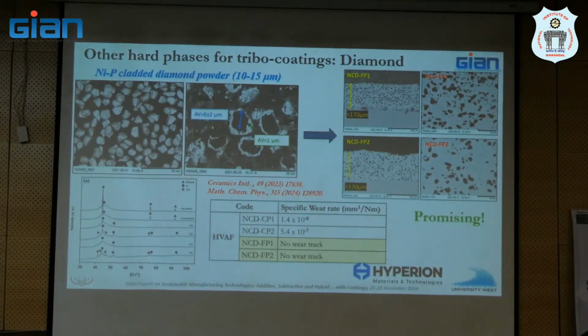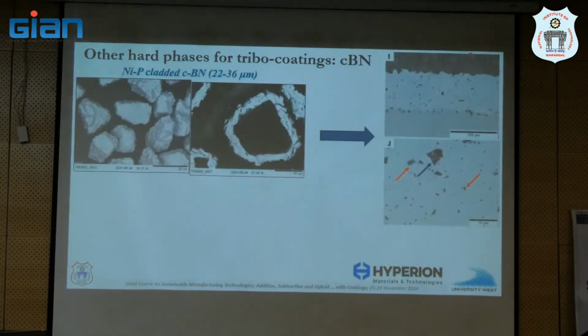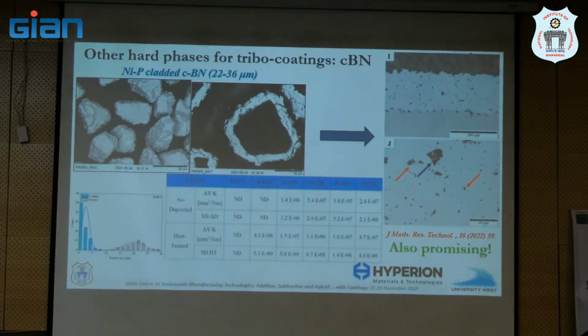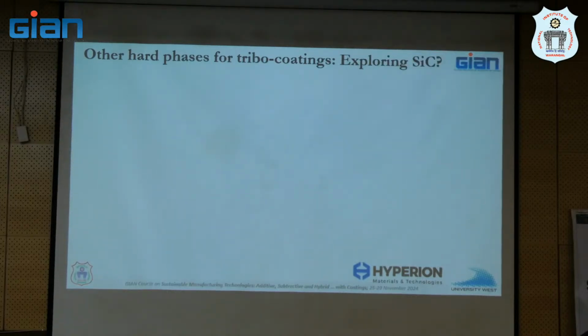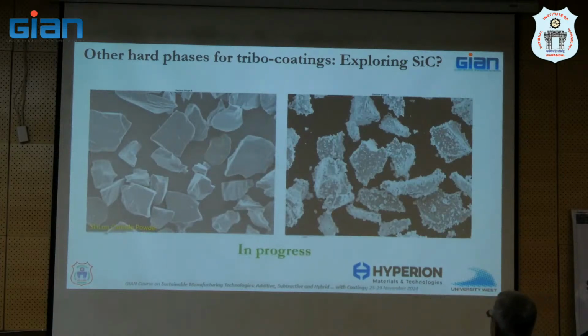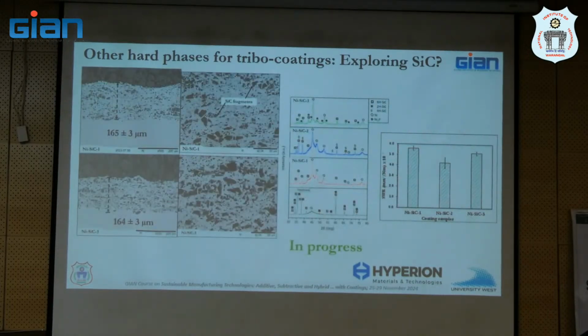And because of that, we also got encouraged to look at cubic boron nitride. We have kind of done the same. Again, pretty nice properties, right? 10 to the minus 8, 10 to the minus 7 specific wear rate. So this is also something we have published. But the next step for us is silicon carbide, because this is cheap. I don't mind losing 80% silicon carbide when I'm spraying. I don't want to lose 80% diamond or CBN, but silicon carbide I don't mind losing. So this is something we have started doing. Had them try and coat nickel phosphorus on SiC. They are not so successful, but the coatings are not bad, and so this is something that's in progress.